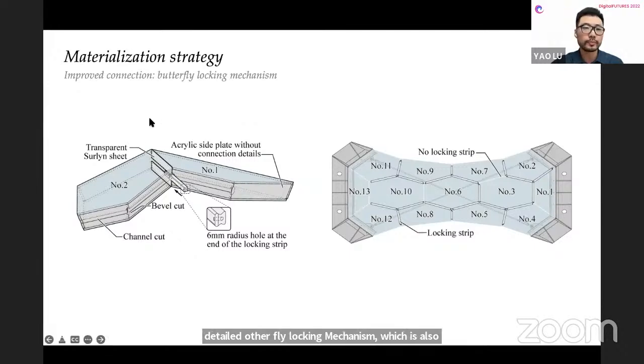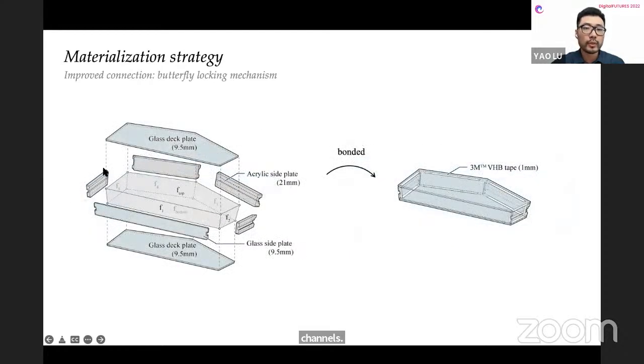the final construction. It has a locking strip made of acrylic, and also the channels on the 2 hollow glass units that it is trying to bring together. So the side plates with the channels will be very difficult to make using cast glass and water jet cutting. So we decided to use acrylic and 5-axis CNC milling instead of casting. And as always, we bound all the parts together using the 1 millimeter thick 3M VHB double-sided structural tape.